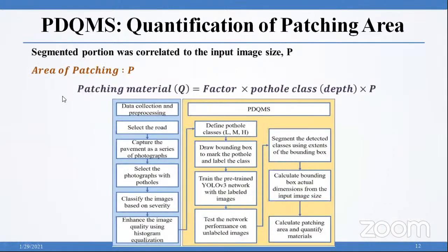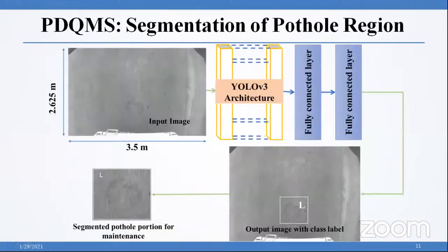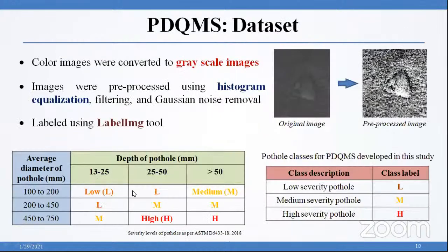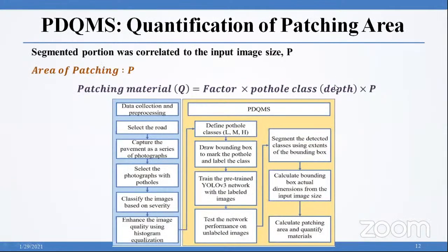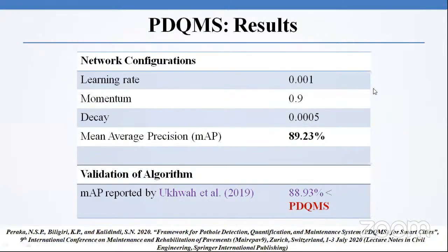area was approximated. And then the quantity of patching material was found as a factor, including the dry volume of the materials before compaction, the patch depth: patching area multiplied by the severity of the pothole, which is nothing but the class level. Based on the class level, we would be able to identify what is the depth of the pothole. So by multiplying these three, we will be achieving the amount of patching material required to do the maintenance of the pothole. So these are the results, and this work has been published in an International Conference in 2020.